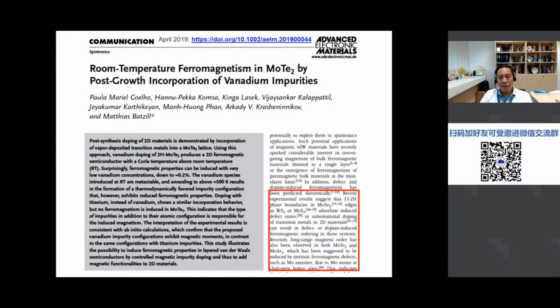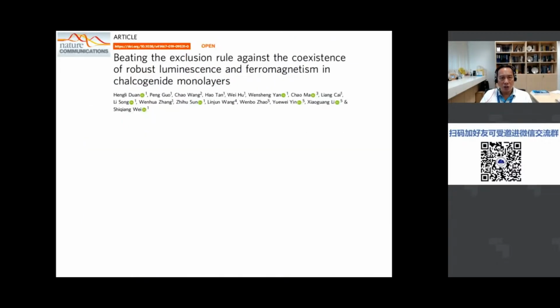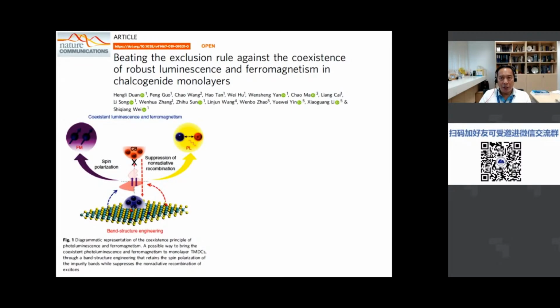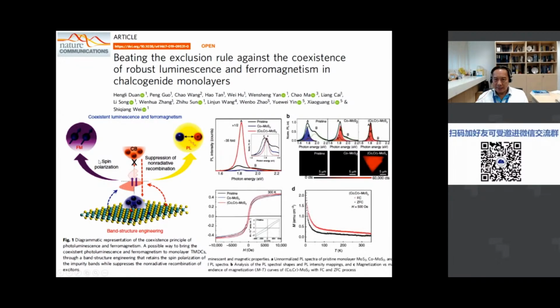And several other people in different systems. So this is a Nature Communications article that appeared, I think it was last year, showing that you can induce both luminescence as well as ferromagnetism in MoS2. And that's a diagram showing the mechanisms involved. Because of suppression of non-radiative recombination, you can get PL, and because of spin polarization, you can get ferromagnetism. And the data is here, but I'll concentrate on the ferromagnetic.